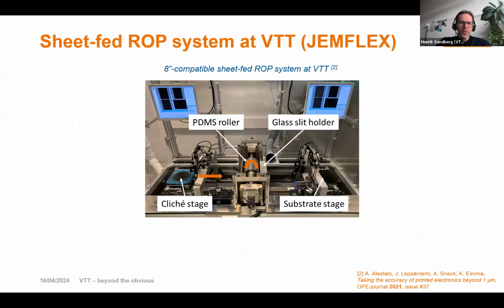This is how the system looks in practice. So we have the cylinder in the middle, which is stationary. There we attach the PDMS onto the roller, and we have the glass slit holder beside to handle the coating when the cylinder is rotated. And then we have the cliché stage on the left and the substrate stage on the right. So these travel on the same translational stage beneath the PDMS cylinder.